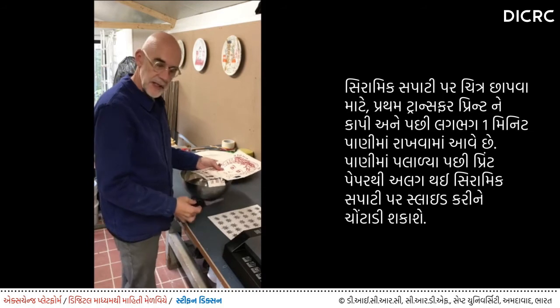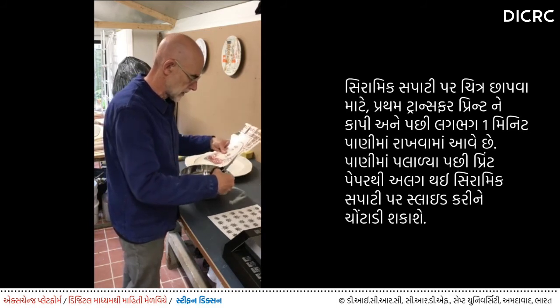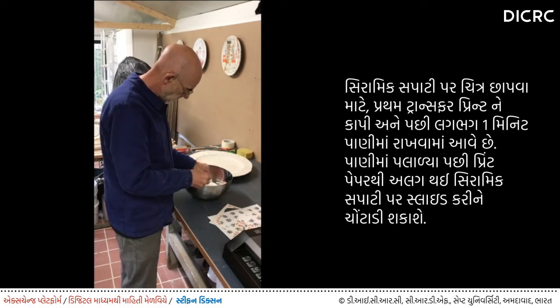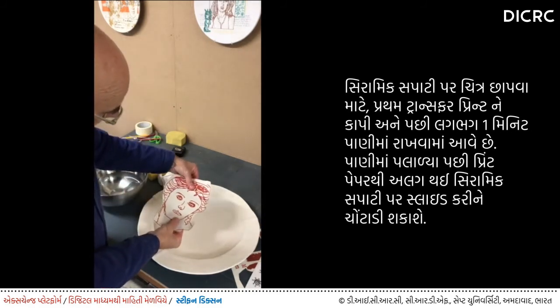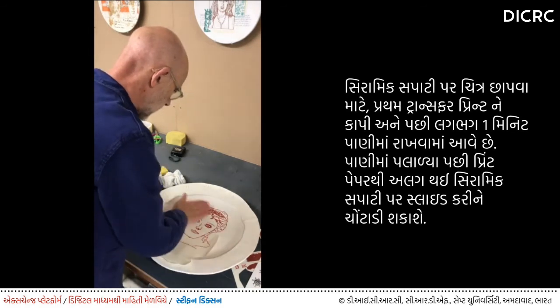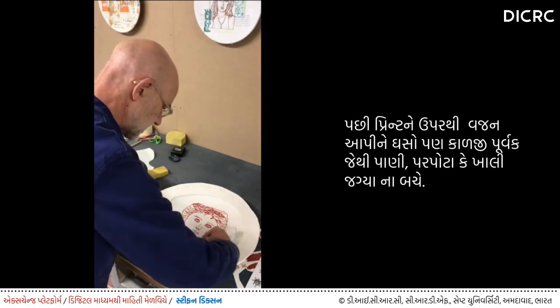To apply the transfer prints to the ceramic surface, they're first cut out and then put into water for about one minute. After soaking in water, the print will separate from the backing paper, and this allows you to slide it onto the ceramic surface. It's then rubbed down very carefully to remove any moisture, water, and air bubbles.